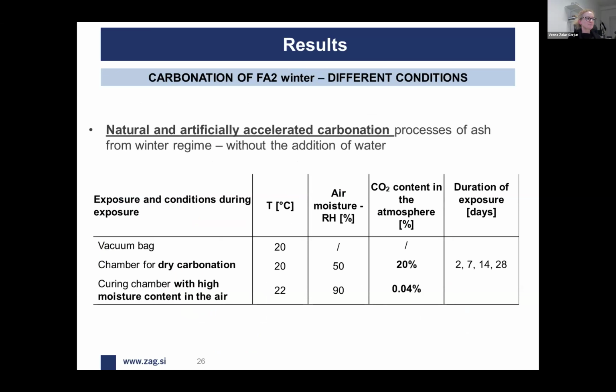So further, we took steps to define the characteristics of this ash in the incorporation, or sequestration, of CO₂. We used 3 different exposure conditions. The first one was a vacuum bag, as a reference. The second one was a chamber for dry carbonation, so air moisture was only 50%. And the third one was chosen with higher moisture content and lower CO₂ content, just to check what influences more, either a higher content of CO₂ or a higher content of air moisture. And different exposure times were used.